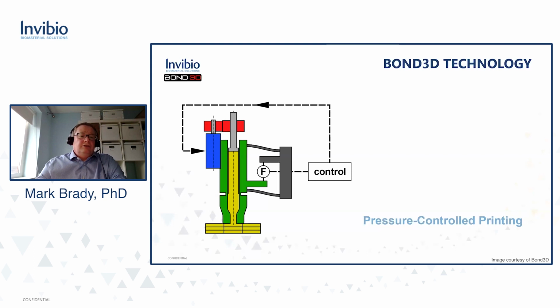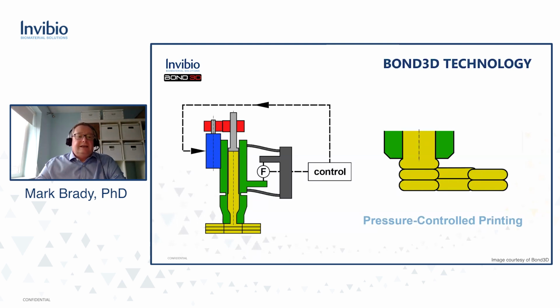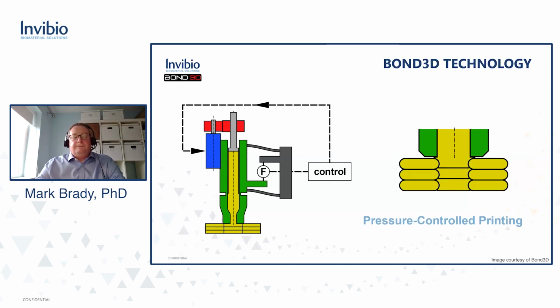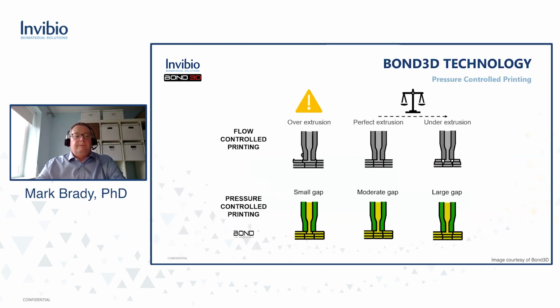The Bond technology uses alternating traditional flow control printing with pressure control printing to achieve virtually voidless parts. Flow control is used to deposit tracks either side, and then a pressure control printing track is deposited between to achieve perfect fill. This is all controlled via a feedback loop between the force applied to the feedstock in the feeder and a preset pressure value that's experienced in the melt pool between the nozzle and the substrate. What that means is that via the pressure control printing process, you can achieve perfect fill of small, medium, or large gaps between the flow control lines.